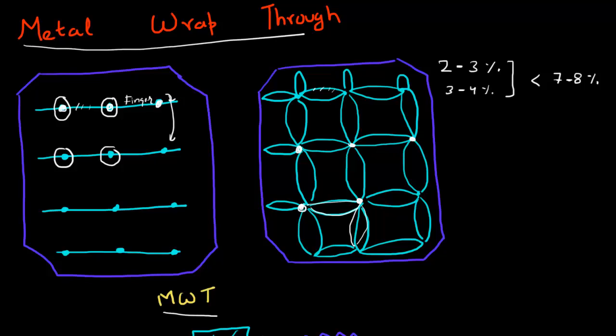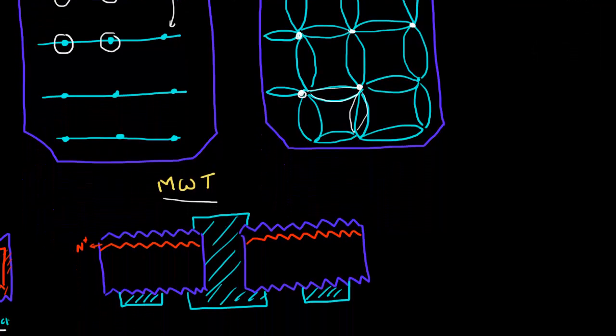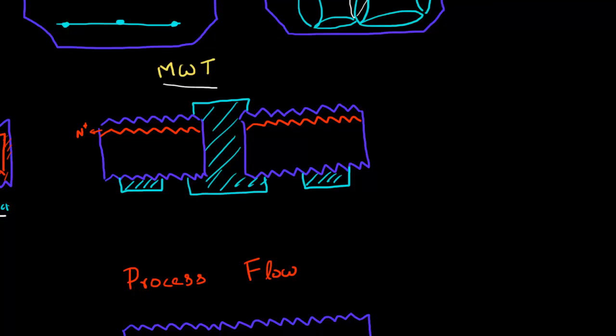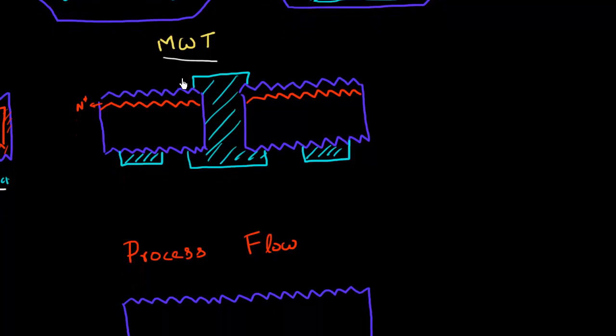So it's good to take a peek under the hood and take a look at the cross section of this cell. So it starts like a conventional cell. So you have this, in this case, this P type wafer and then you diffuse, you form this N plus emitter diffusion at the top. So this would be your N plus diffusion over here. And then you drill holes into this and you fill it with metal which is contacting the fingers at the top. And now these fingers are now routed towards the back,